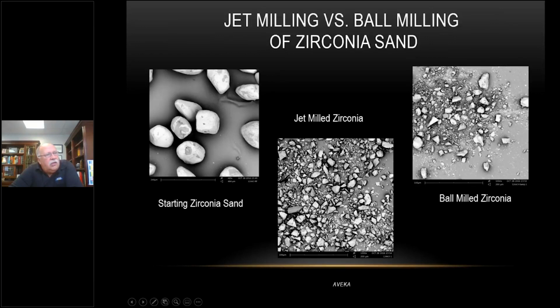And if you look at the ball mill SEM picture here, you can see we've got the right size, but lots of fines. And so in this particular case, as opposed to the jet milling situation, even though you could get the right size with ball milling, which is a cheaper process to use, by the way, I don't discount ball milling as a great way to do it.